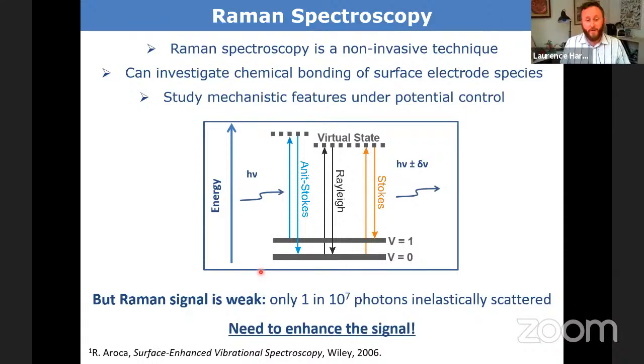Now, for conventional Raman, even though this sounds very small and I say the signal is weak, it's still strong enough for us to get very good Raman spectra of a whole host of different materials. But if we wanted to look at surface adsorbates, monolayers of materials on a surface, we really need to enhance the signal, because if we want to look at really small concentrations of species, the standard Raman effect is way too weak.